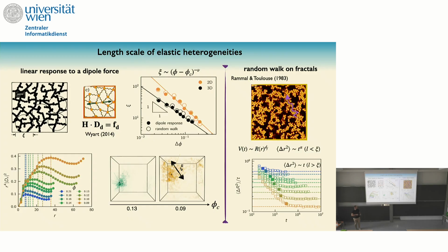Then you measure the mean square displacement as a function of time. And if you normalize that by what you expect from the diffusive behavior, which would go as t, you see that below this length scale the system is subdiffusive, and then at some point it starts to be diffusive. And again, here you define a length scale by taking the crossover between the subdiffusive regime and the diffusive regime.